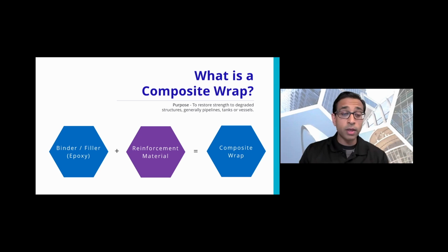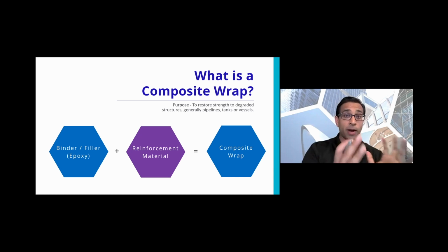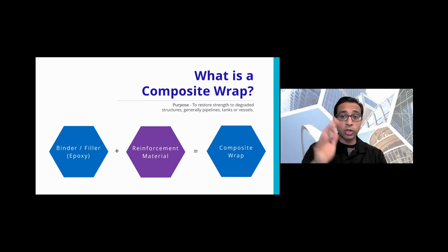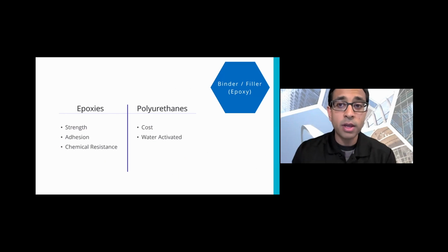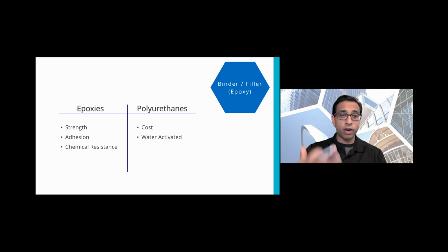It's pretty cool. So what is it made of? It's made of a binder or a filler, right? That's actually the epoxy. A reinforcement material, and you add those two together, you get a great composite wrap. And for binders, we always recommend epoxies. You could use polyurethanes. Here's the issue with polyurethanes. They're very expensive, and they're also activated with water. And the fact is that when you have those two things, you've got a lot of cost associated with it. When you compare that to the strength, the adhesion, and the chemical resistance of the epoxy, epoxy is the way you're going to want to go.